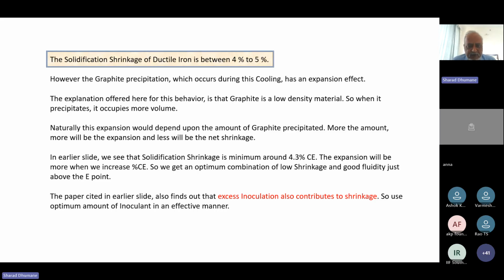Now we have understood how ductile iron shrinks. It shrinks in a mushy zone. There is a freezing range. As the carbon equivalent increases up to 4.3, the freezing range goes on decreasing and the solidification shrinkage goes on decreasing, and then after 4.3, it increases. So now we have some information about ductile iron shrinkage.